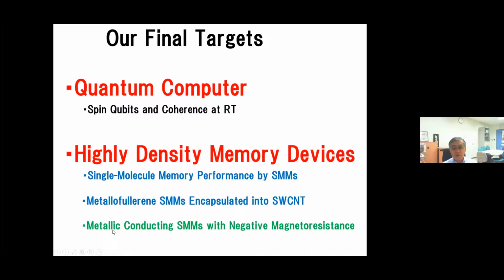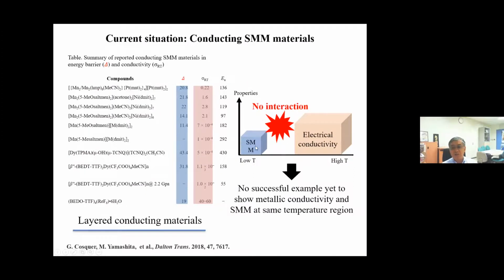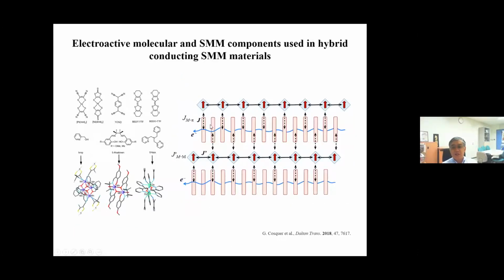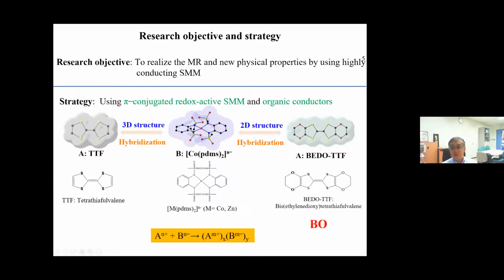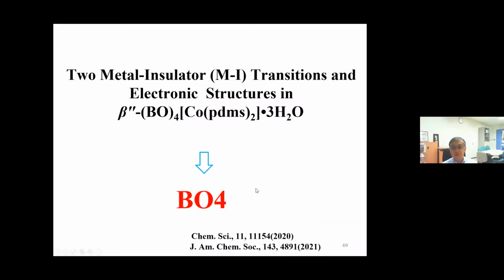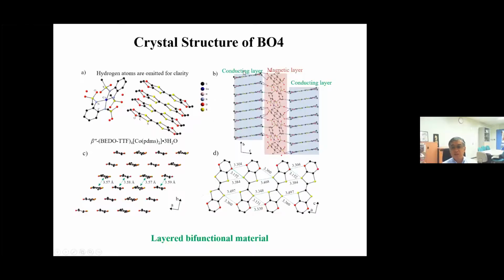So finally, I talk about the metallic conducting single molecule magnet with negative magnetoresistance. So usually single molecule magnet behavior is at very low temperature, and electrical conductivity is at high temperature. We must hybridize these properties to realize the negative magnetoresistance. So we realize the conduction path and the local single molecule magnet interact to show the negative magnetoresistance using these molecules. So in this case, we use a donor, BEDO, an organic donor, and the cobalt single ion magnet combined by the electrochemical method. Yes, this compound. So the conduction path BEDO and the single molecule magnet interacted.